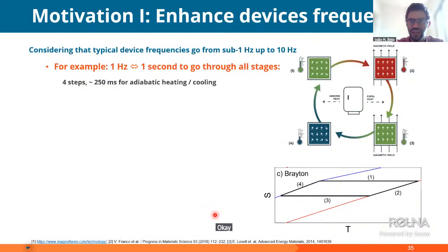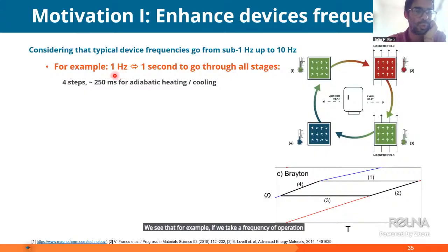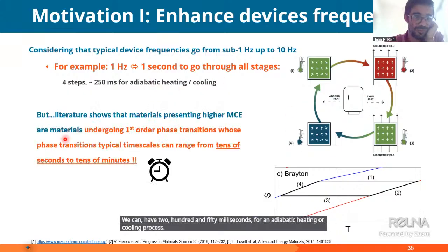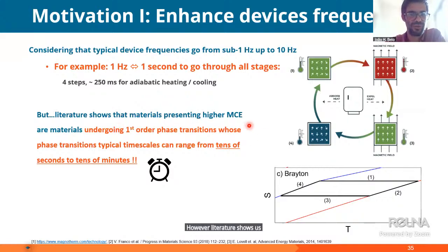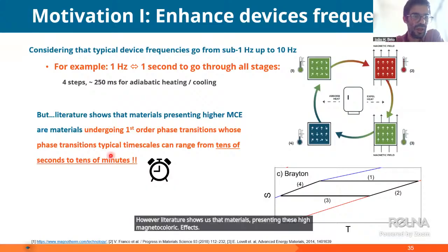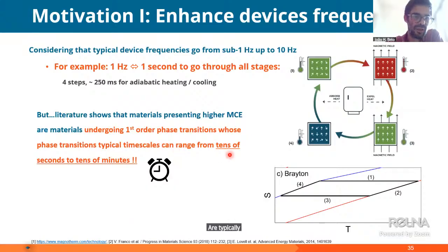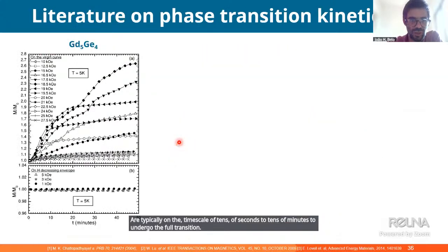Okay, so just taking an example, looking at the full cycle represented here, if we take a very low frequency of operation, 1 Hertz, one would need 1 second to go through all 4 stages. So there are 4 stages, meaning that in a rough estimation, we can have 250 milliseconds for an adiabatic heating or cooling process. However, literature shows us that materials presenting this high magnetocaloric effect are typically on the time scale of tens of seconds to tens of minutes to undergo the full transition. So this is really an important issue.